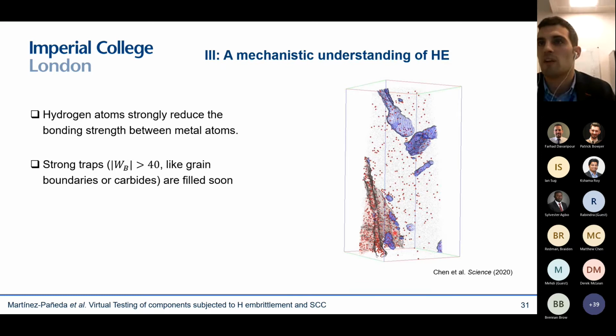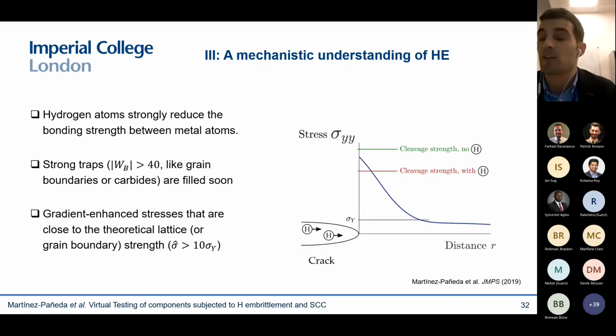And this red thing here is the grain boundary. And you can see that there's quite a lot of hydrogen atoms that get accumulated in the grain boundary. It's just full of hydrogen atoms, basically, the grain boundary. And the last ingredient is to couple all of this with this enriched crack tip mechanics description that I was